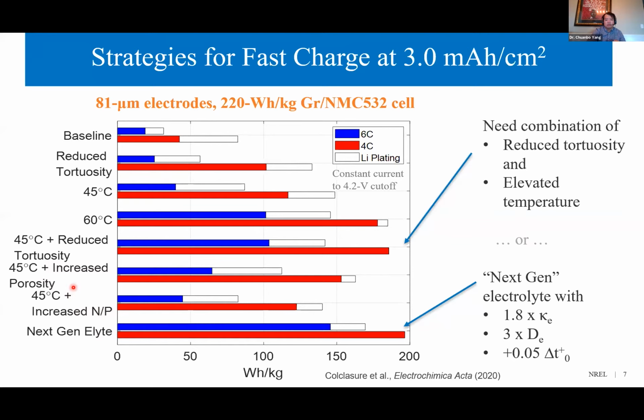For a loading cell with 3 milliamp hour per centimeter square, the combination of operating at 45 degrees Celsius with an electrode having reduced tortuosity enables energy densities of 186 and 102 watt-hour per kilogram during 4C and 6C constant current charge, and can be a very viable near-term technology.